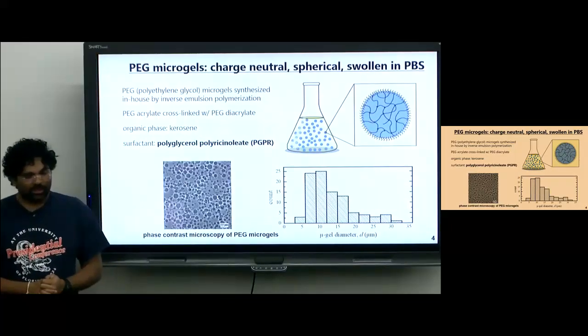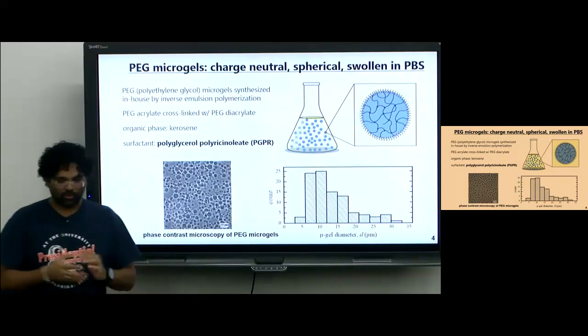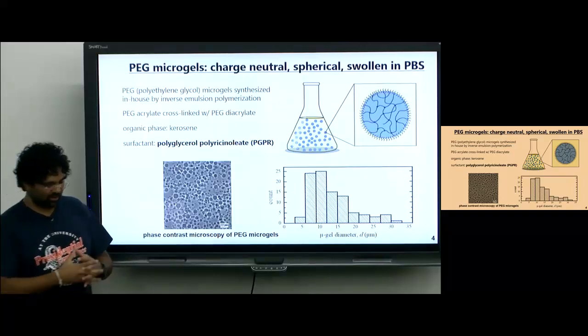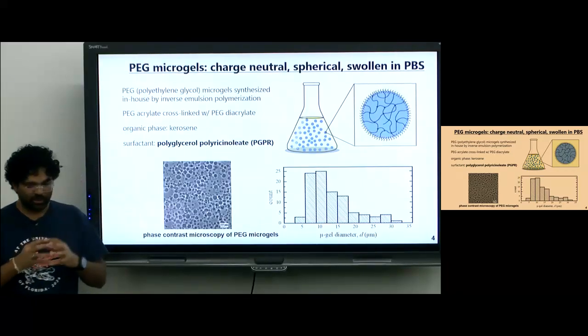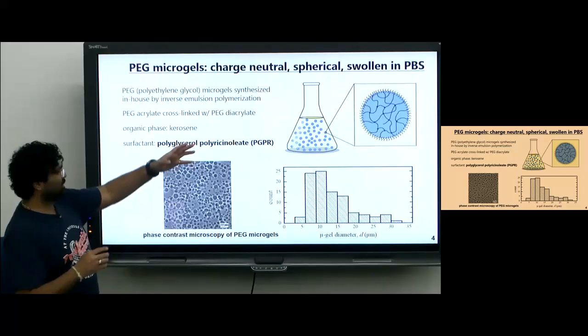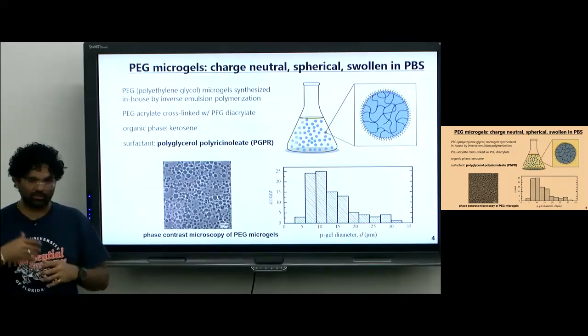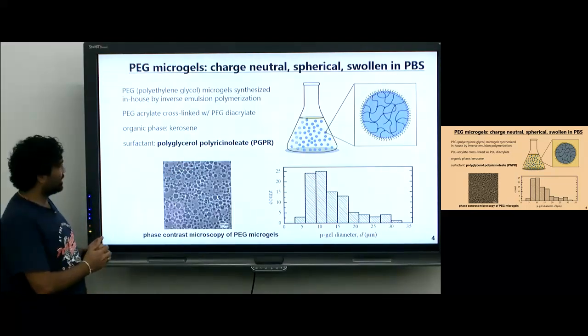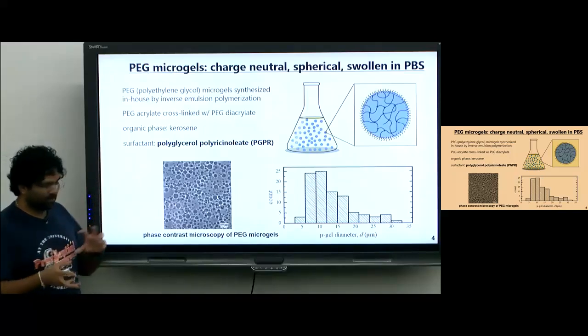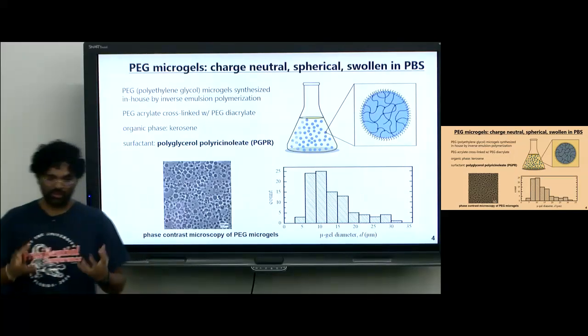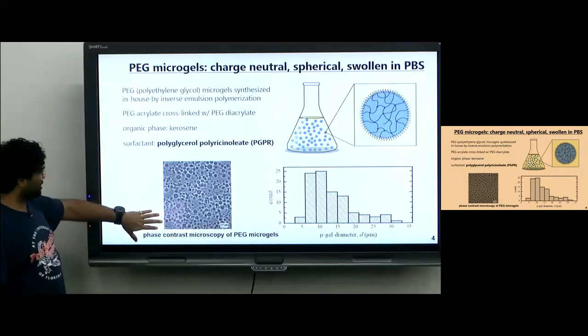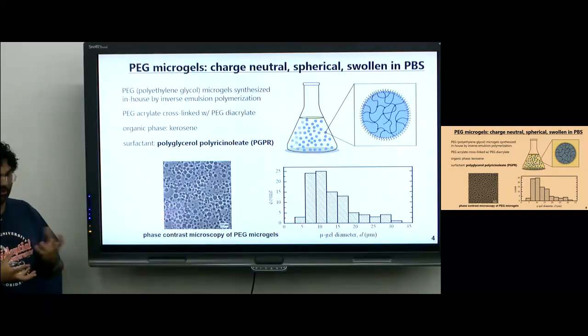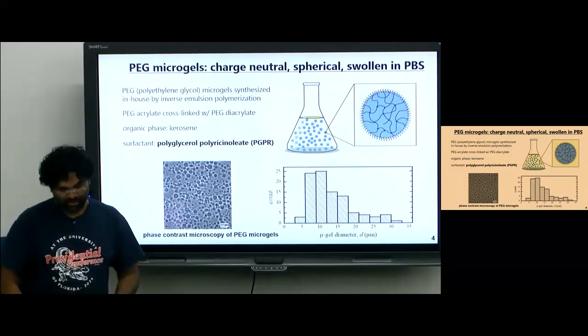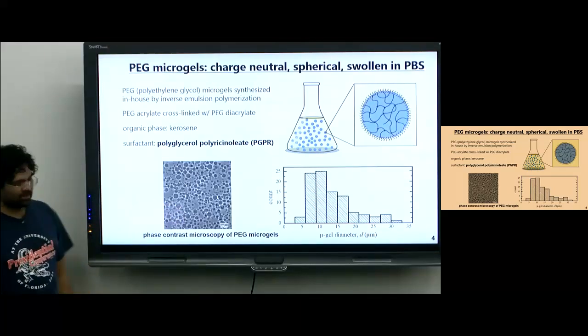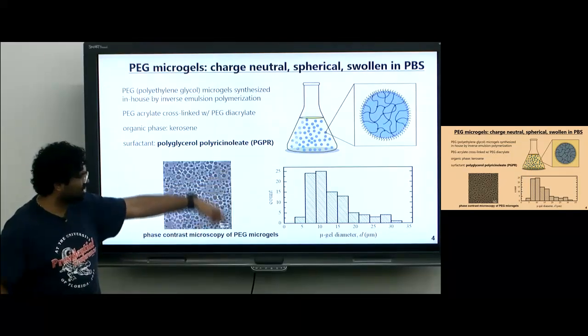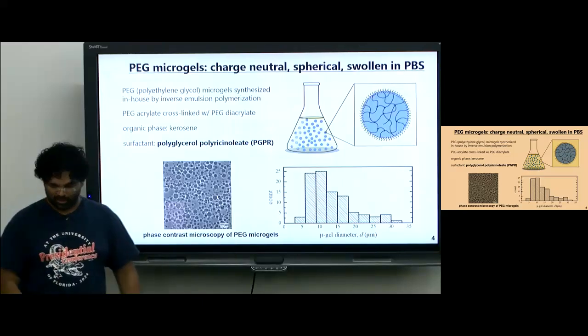I was talking about microgels, right? So for all of this work, what enables us to do this is these packed soft particles, swollen in this case not in PBS, but in the cell growth media itself that the cells need to proliferate. They're made of polyethylene glycol in an inverse emulsion polymerization method. And here is a microscopy image of how these microgels look. It's packed, soft, spherical particles, and they have an average diameter of 8 to 10 microns and a distribution of about 5 to 40 microns.